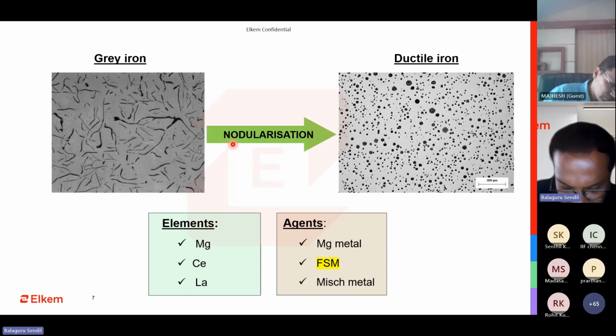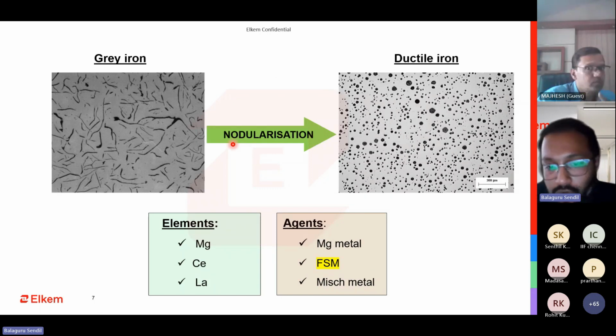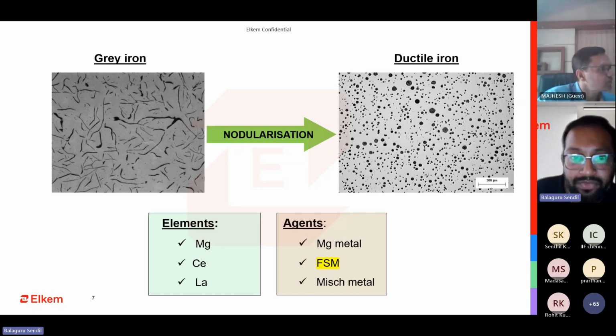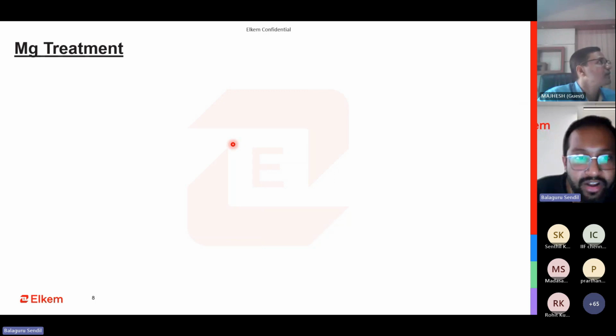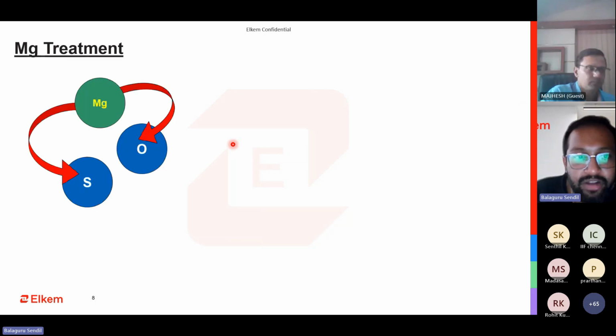How they cause that effect is that they are able to adjust the growth rate between the basal and prismatic plane so that you get a nodule. But how do you introduce all these elements? These are the sources in which these elements can be introduced. The next one is magnesium treatment. When you are doing magnesium treatment, I've showed you the schematic structure. What is a nodule? In the core of the nodule, you have a magnesium sulfide and a magnesium oxide core. So the magnesium goes and reacts with the sulfur and oxygen in your metal.